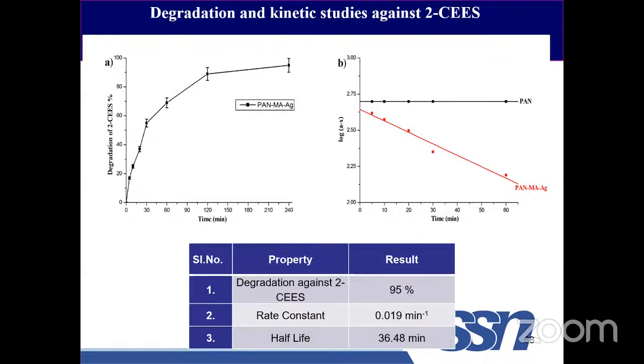And we checked the degradation of the chemical agent. We can't use chemical agent directly because of clinical issues. So we chose simulant 2-CEES, that is 2-chloroethyl ethyl sulfide, which is a simulant for sulfur mustard, where 250 ppm is the LD50 value. We have taken 500 ppm and tested its degradation efficiency with the prepared membrane. As you can clearly see, 95% of the 2-CEES that we take at 500 ppm is being degraded. When we studied the kinetics, the rate constant is about 0.019 per minute and the half-life is about 36 minutes.